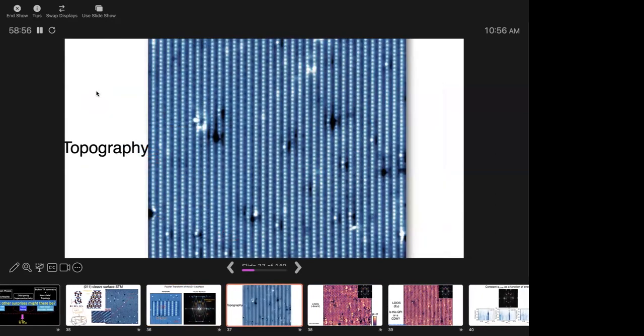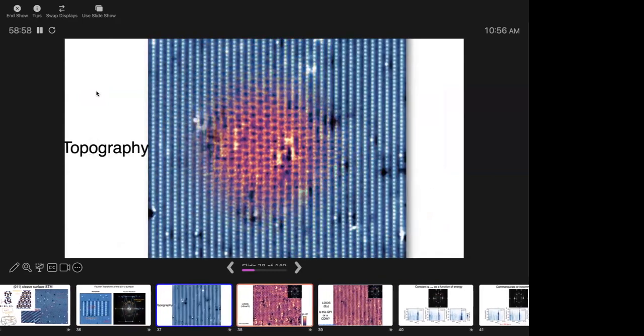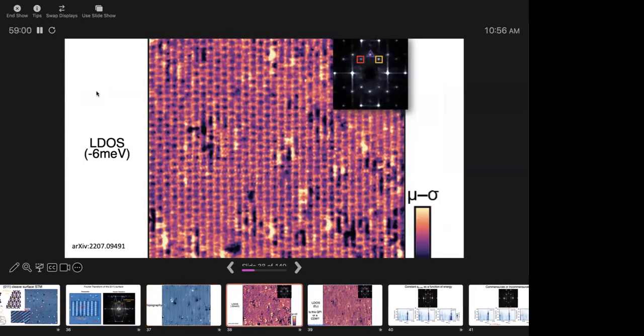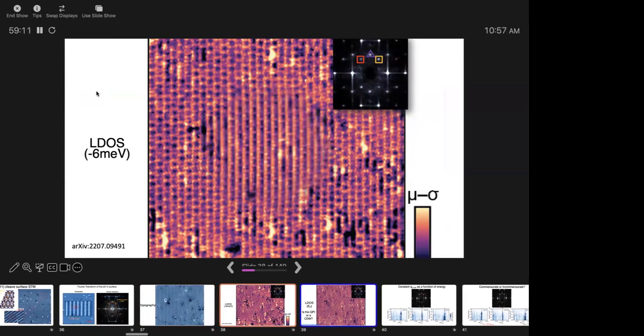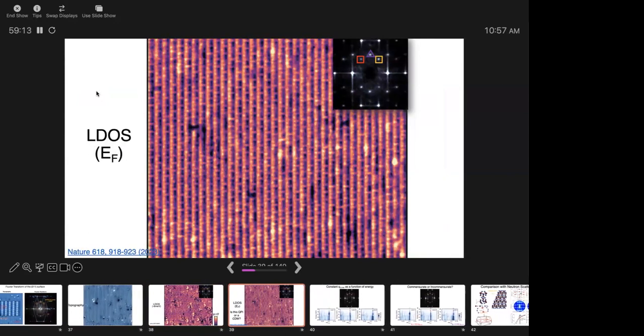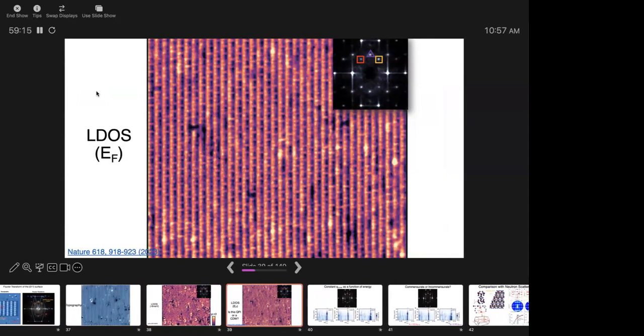If you look at dI/dV maps, so this is the topography, this is the dI/dV map at one energy. Actually, this is dominated by this peak here. This is the Fourier transform of this dI/dV map. You can see these stripy features that you couldn't see in the topography. And then at the Fermi energy, close to the Fermi energy, you see these, that's dominated by these 2.